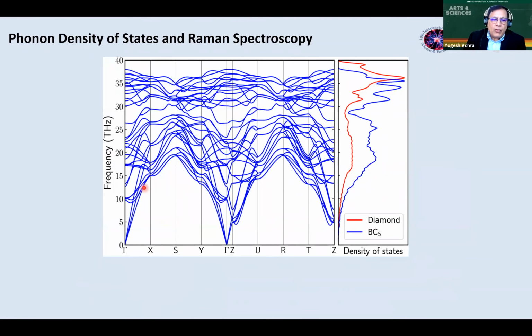So these are the phonon calculations, and on the right side are the phonon density of states. The red curve is that of the diamond, and the blue curve is that of the BC5 material. Very qualitative observations are that the phonon spectrum is shifted downwards, but it also has more structure, and we should be on the lookout for these additional peaks in our Raman spectroscopy.